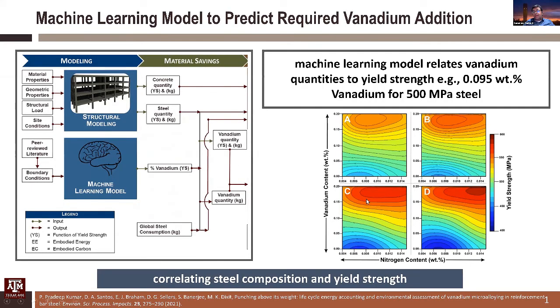So one of the things that we did is we actually mined the literature, because as you know, there are many different types of compositions. Each mill has a different composition. Each mill has a slightly different feed ratio. So we came up with a machine learning model where we fed a lot of the primary literature on rebar or steel sections. And we were able to come up with some models correlating steel composition and yield strength. So at different concentrations of vanadium or nitrogen, we could come up with a multi-dimensional model so that we're not using just the ratio for one company, but we are using it across the literature, right? So what are the consensus values?